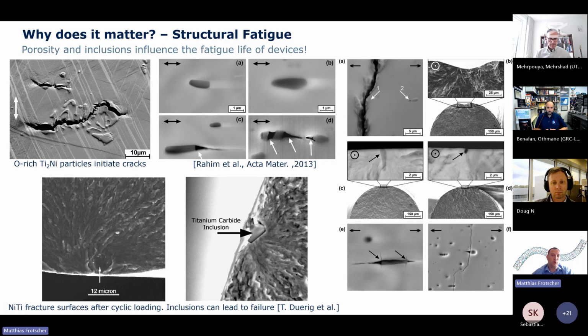That's why it is interesting to know, for example, what the nearest neighbor distance between inclusions is. The smaller this distance is, the easier it is for the crack to propagate. And then there was a nice paper by Rahim et al. in Acta Materialia about this phenomenon.